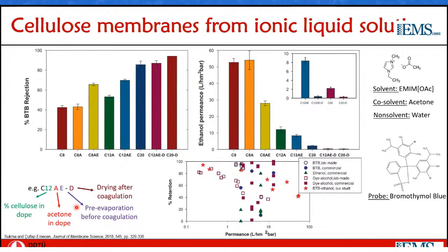And so we made cellulose membranes from ionic liquid solutions, where our ionic liquid was this ethyl methylimidazolium acetate, a room temperature ionic liquid. We had acetone as a co-solvent and water as a non-solvent. Here you see a number of membranes and their performance. In the membrane codes, this number stands for the cellulose percentage in the polymer solution. A stands for the presence of acetone in the polymer solution, up to some 20-25%.